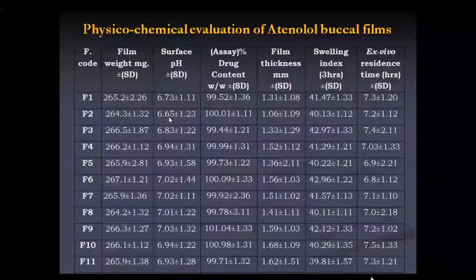When moving on to swelling index, the swelling index is usually done on a hot agar solution. I have to transfer it into the petri plate and wait for some time to get solidified. Then later on, we have to move the film onto the solidified agar medium, so that the water from the agar medium can go into the film, and the film can absorb the water, so that we can check how much water can be absorbed by the film. That we can do with the help of hot agar solution.